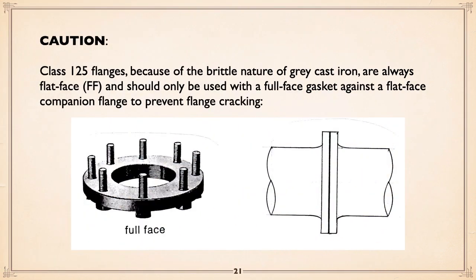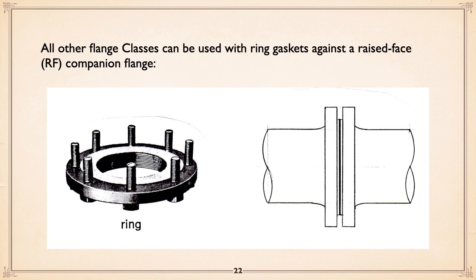Now, class 125 flanges, which means cast iron, gray cast iron, are always flat-faced. That's because of concern of cracking if you don't go with a full flat face flange and a full gasket. All other flange classes, including the 250 gray iron, you can use a raised face, which, as you can see, gives you more pressure over a specific area, and an insert, what they call a ring gasket, because you're not worried about cracking the thing by over tightening the bolts.